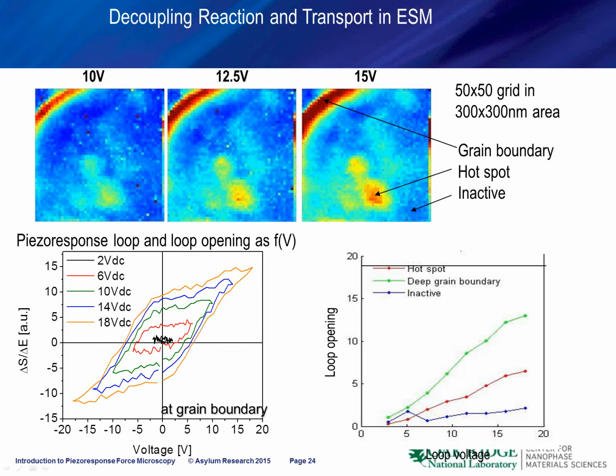That's exactly what we can do using these first-order reversal curve measurements, where at each location we measure a set of hysteresis loops. An example of this data is shown in this slide. You can see the progression at a single point from closed to open loops. And these images are perfectly correlated in space because we measure them all at the same time. We can visualize the difference between the loop opening for inactive regions, so it's kind of one slope, for the hotspot on the material surface, where you see a higher slope, and the grain boundaries, with the bigger slope.